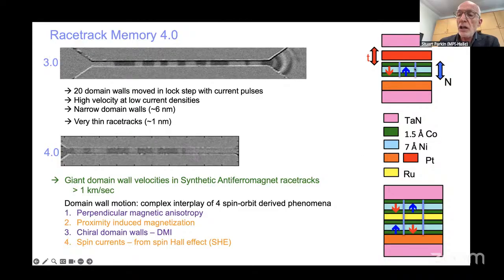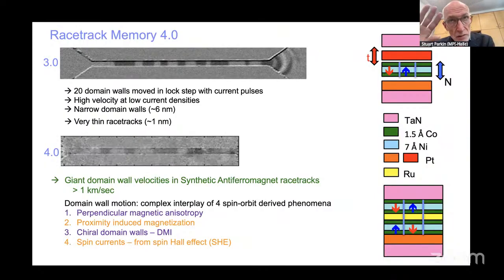It consists of the same cobalt, nickel, cobalt layer in the top, but there's a second cobalt, nickel, cobalt layer separated from the first one by the yellow layer formed from ruthenium. And in 1990, I demonstrated for the very first time that through nearly all the transition metals and the noble metals like gold and silver, all these metals become spin polarized when they are placed adjacent to a magnetic film, and the spin polarization is oscillatory, and this leads to an oscillatory magnetic coupling.